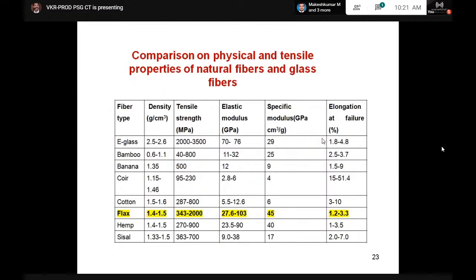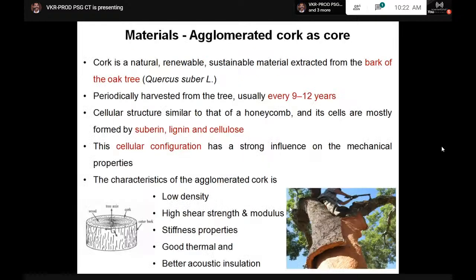You can see the properties where the E-glass modulus is around 70 to 76, and the flax fibers range from 27.6 to 103 GPa. So this is really a candidate for replacing glass fibers. Since glass fibers are extensively used, we thought, okay, let us find an alternative available in the natural fiber so that it can be used. And we took cork as support. This is another natural material available for us to use, which has low density, high shear strength and modulus, better stiffness properties, good thermal and better acoustic insulation.